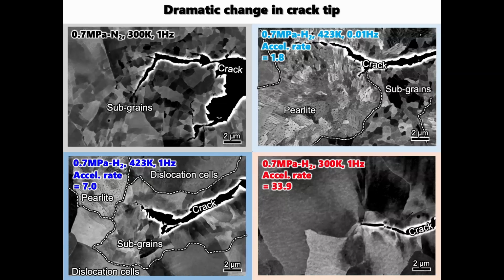The other is the different fatigue crack growth rate generates the different cumulative plastic strain ahead of the crack tip. So a location is subject to the different number of loading cycles when fatigue crack growth rate is different. So we should pay attention to this fact. But it is quite likely that the hydrogen drastically changes the plasticity during fatigue process. And its effect is strongly dependent on the temperature and loading frequency.